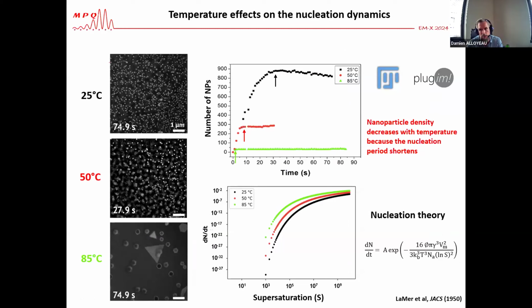And the first thing we have done is quantify the nanoparticle density. And you see that at 25 degrees, you have several hundred nanoparticles in your observation area. At 50 degrees, only 300, and only 30 nanoparticles are formed at 85 degrees. And you realize that, in fact, the nanoparticle density decreases because the nucleation period is much shorter. So when you now look at the nucleation theory, this is the equation that gives you the nucleation rate as a function of the supersaturation and at different temperatures. You see that our experiment is not in agreement with this nucleation theory because we expect to have a higher nucleation rate at higher temperature, which is not the case in our experiment.